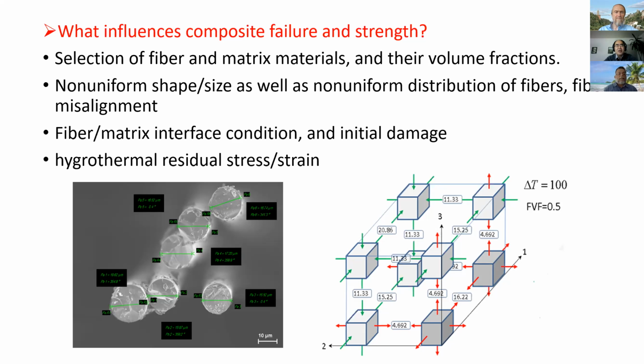And also there are some initial damage, such as micro voids or some debonding between the fiber and matrix during the fabrication process, and those are also going to affect the failure. Another one is going to be, for example, thermal residual stress during the fabrication or during the change of temperature with the constraint in the layer of the laminate composite.